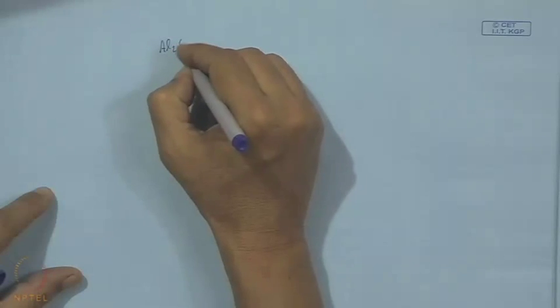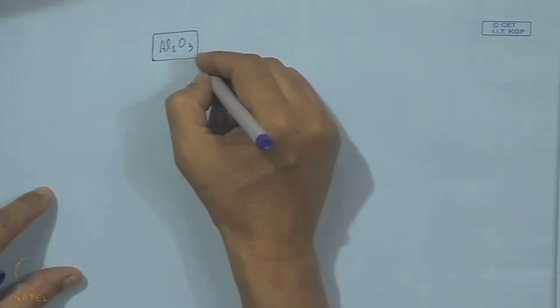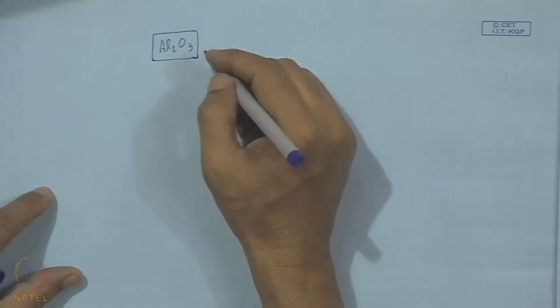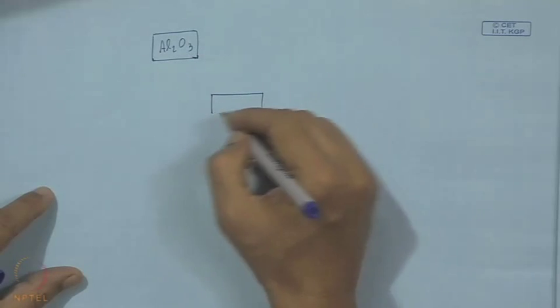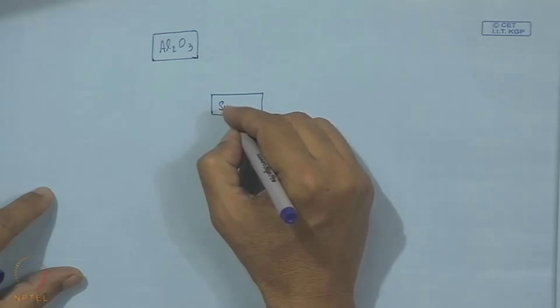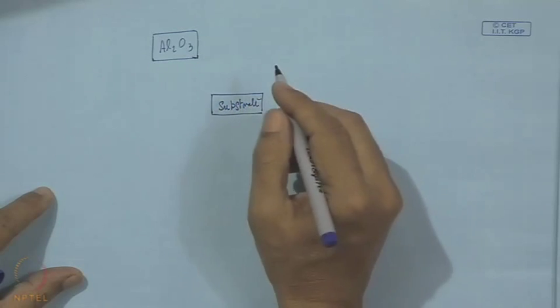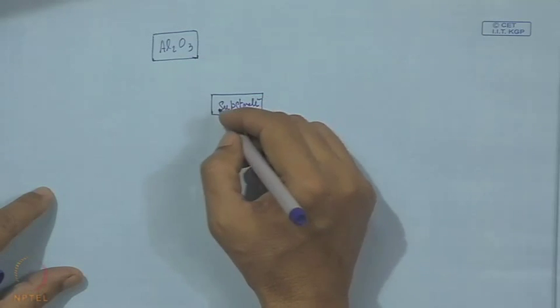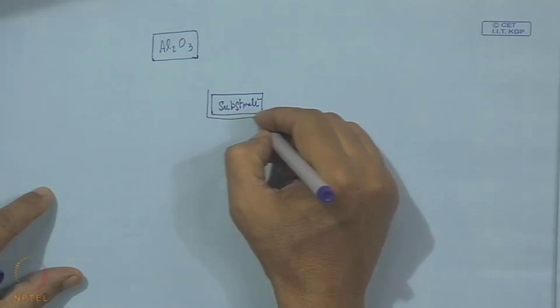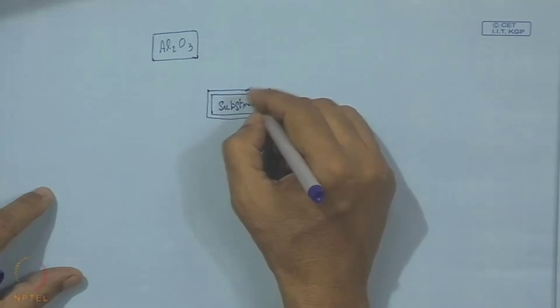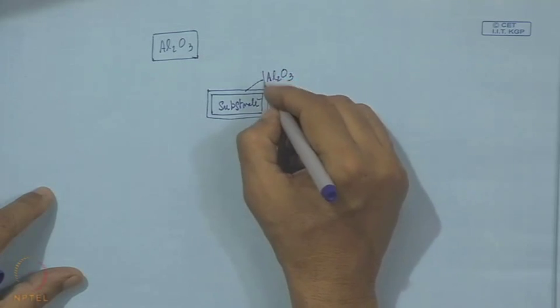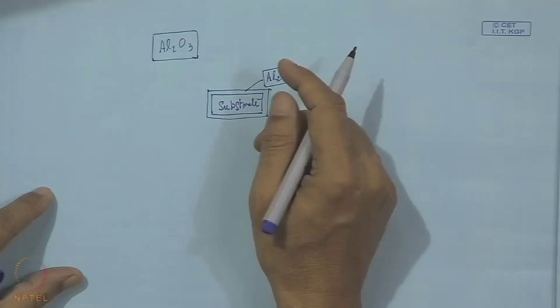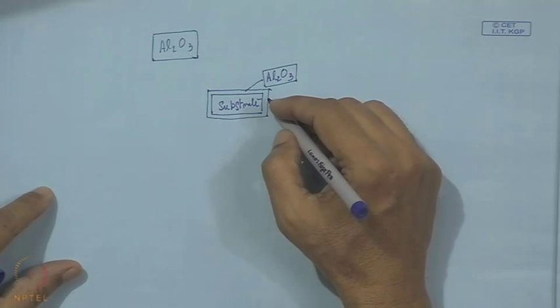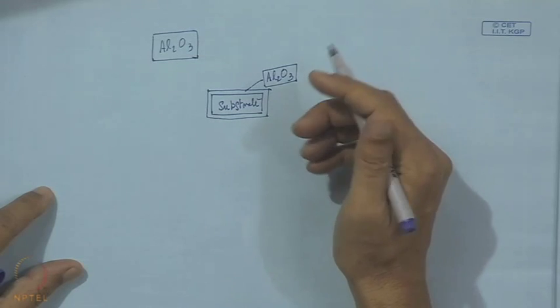That is why the whole idea here is that if we can have this aluminium oxide, which has all the required properties, namely chemical and thermal, and put it over a substrate made of tungsten carbide cobalt or similar material in the form of a coating, then the whole purpose is served, and here we have one of the best candidates in the form of a coating which can perform its task very efficiently, that means its use as a cutting tool.